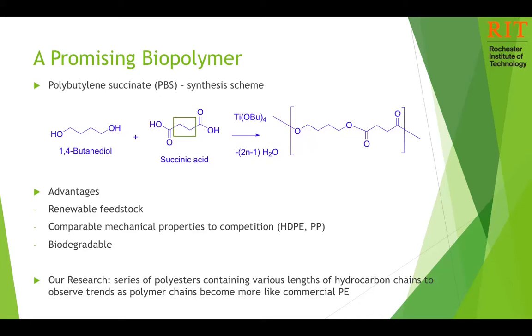Our research involves synthesizing a series of polyesters similar in structure to PBS, but with various lengths of hydrocarbon chains between the carboxylic acids, as shown in the box. Therefore, we can observe trends as the polymer chains become more like polyethylene, whose structure contains entirely hydrocarbons and has notoriously poor degradation. Essentially, we are changing the acid with which to synthesize our polyester with.